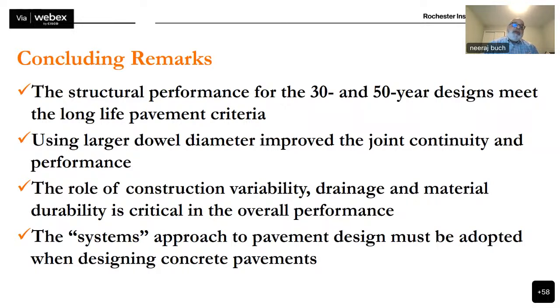So typically pavements that are 250 millimeters thick or higher can have a larger diameter, and pavements that are 250 millimeters or thinner should have a smaller diameter. So I do want to make that clarification. Now, specifically to your question, when you're looking at thin white topping and especially ultra thin white topping, the reason